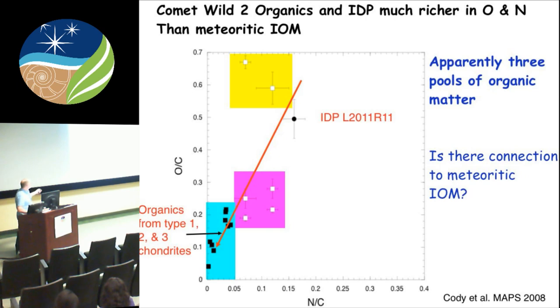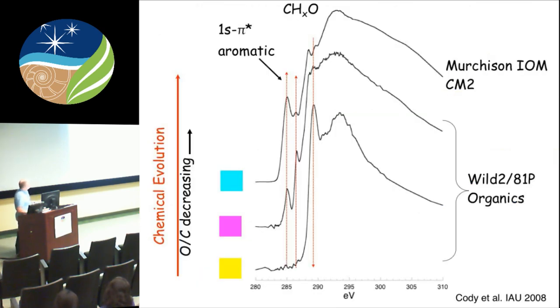And so the question is, is there a trend here? I looked at this back in 2008 and thought I saw a trend. What I saw was basically an apparent evolution where the loss of this peak, which is an alcohol, and the corresponding growth of these two compounds, this is what we call an ene carbon, a double bonded carbon, and this is a double bonded carbon proximal to a ketone. And so clearly it seemed like as this dropped, this went up. And that was familiar chemistry to me. So it struck me that what we were looking at was degradation of sugars. And so that immediately stood out.